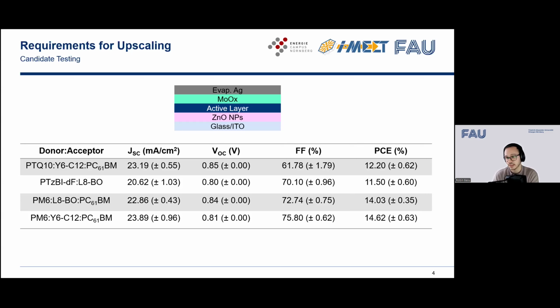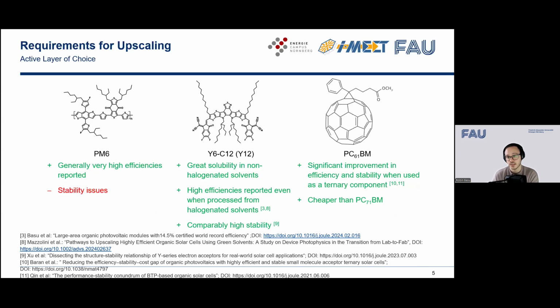However, in the testing stack that we used, we got the highest fill factors and the highest JSC by using Y12 rather than L8BO, which surprised us. So that's where we got an average PCE of 14.62%. So that's why we chose that active layer system for upscaling.